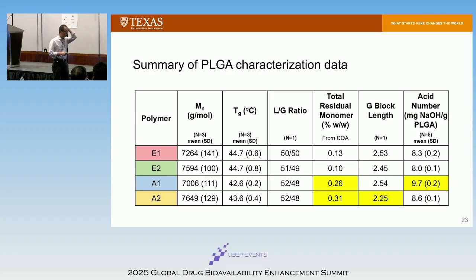I brought up the residual monomer and acid numbers. This actually is very interesting because when we do the extrusion process, those materials get left behind. If you do a microsphere, that gets washed away if I have residual monomers. This actually is one difference we realized later. For the extrusion, whatever you have, most likely they stay.